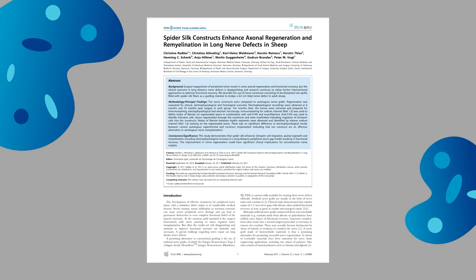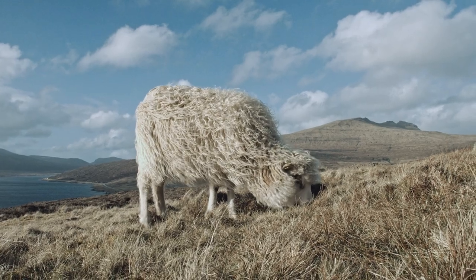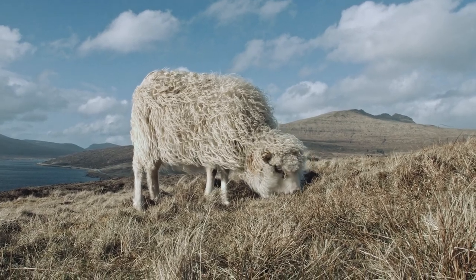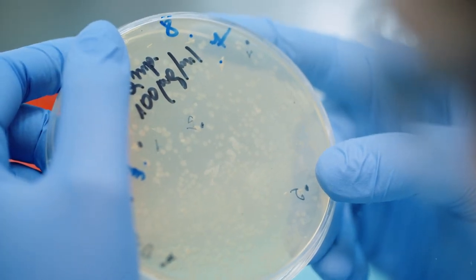But the ingenious properties of spider silk and our relentless innovation have pushed these limits. Scientists have created tubular structures filled with guiding fibers or microchannels, and even encapsulated growth factors, providing a clear pathway for nerve growth. A study by Radtke et al. made a breakthrough in this regard. They used decellularized vein grafts filled with natural spider silk fibers from Nephila clavipes as a guiding material to bridge a whopping 6-centimeter model defect in the tibial nerve of adult sheep. The cultured human neurons in the silk fibers exhibited significant adhesion and migration of cell bodies, as well as differentiation, and extending neurites formed ganglion-like cell structures — marking a major stride in overcoming the challenge of gap length.